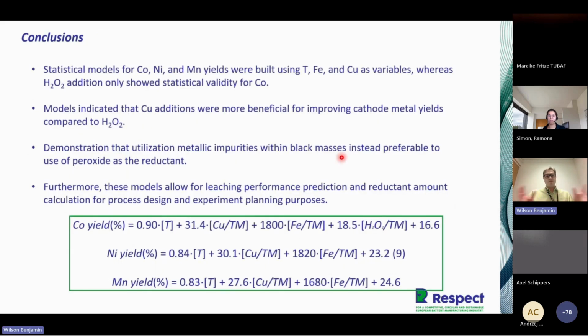So just to finish with some quick conclusions. We showed that you can make statistical models for the cobalt, nickel and manganese yields based on temperature, iron and copper as variables, and also peroxide. These models indicate that copper additions could be more beneficial for improving the yields and recoveries compared to peroxide, particularly at higher temperatures. And it also shows that the metal impurities within the black mass can be used as a reductive agent rather than adding peroxide. So in fact, you can start to reduce the carbon footprint and also exploit some of these impurities within your black mass.